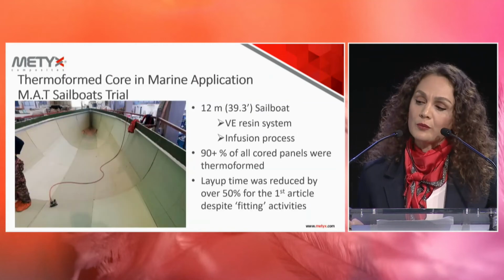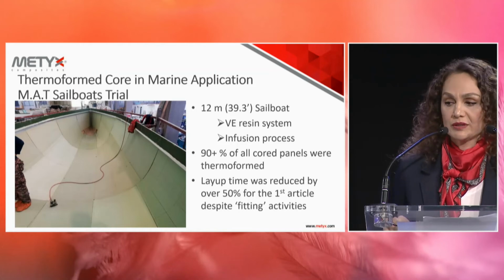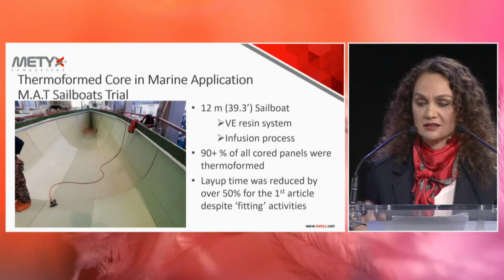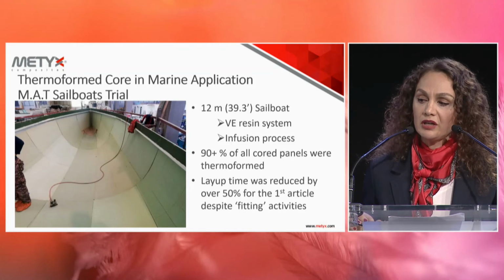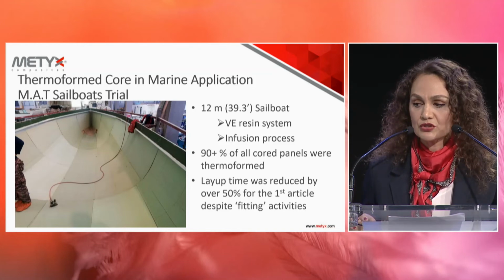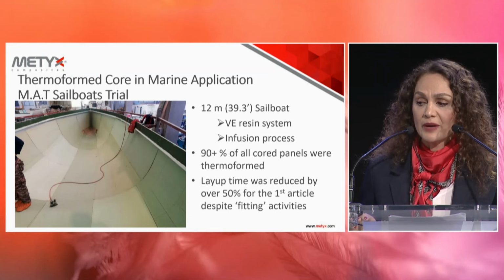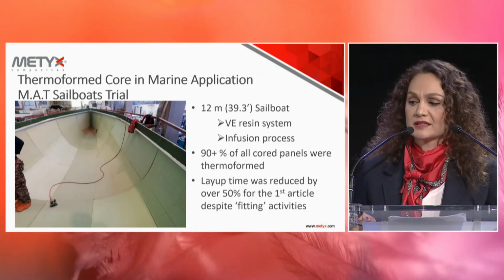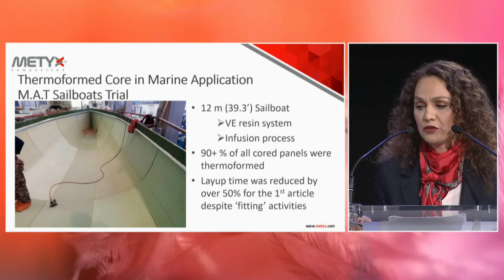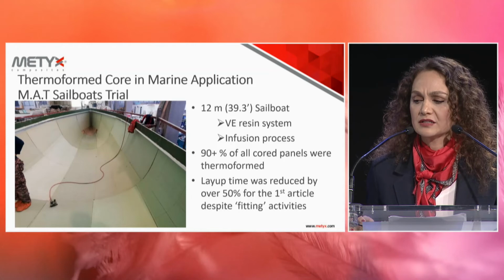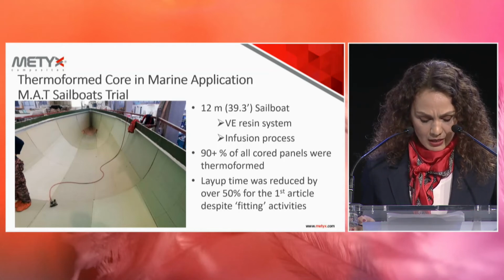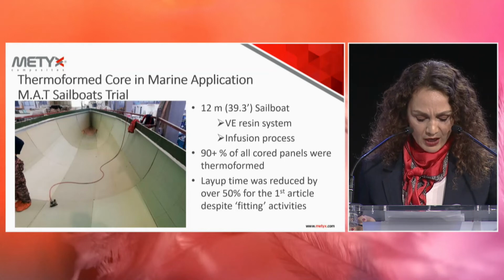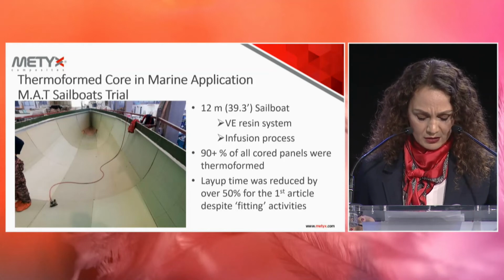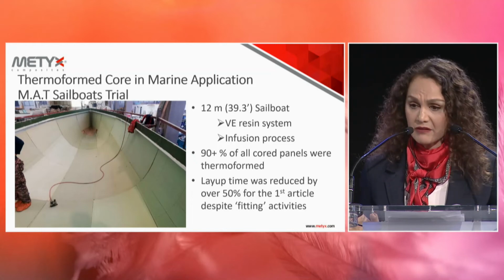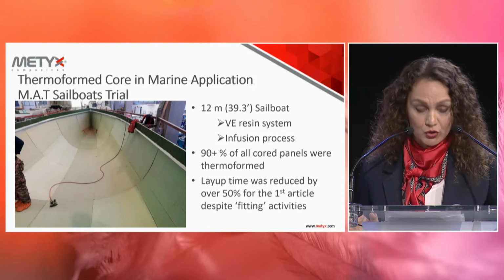So we used this thermoformed core with the adaptive mold in the marine application too. This is another case. MAT is a particular boat builder. So we produced this with the same method, a sailboat, 12 meters long. We used a vinyl ester resin system. So we use the classical infusion process. 90% of all core panels were thermoformed. Not all pieces were formed right, and some of the lengths were a little bit off. Fitting core, fitting part to part, had to be compromised as well. But despite all that, we're still saving over 50% labor time, which is huge for the markets.